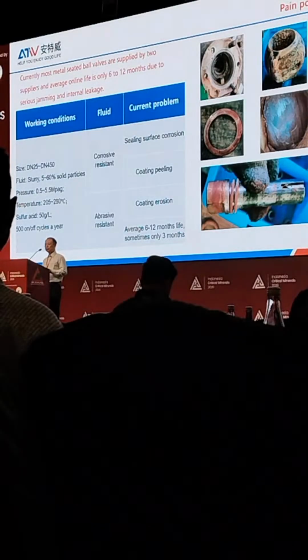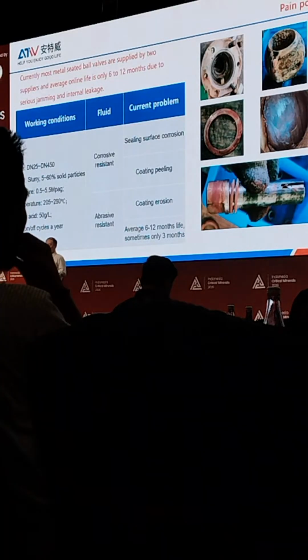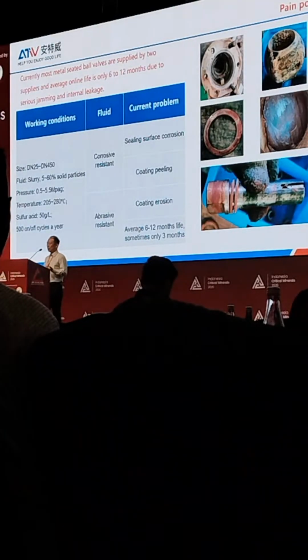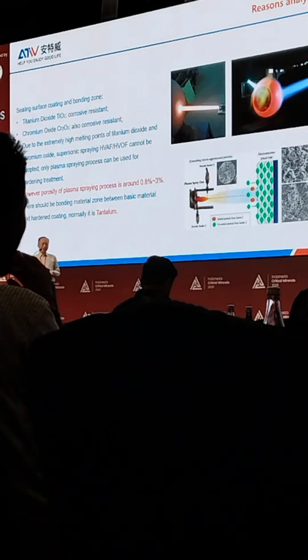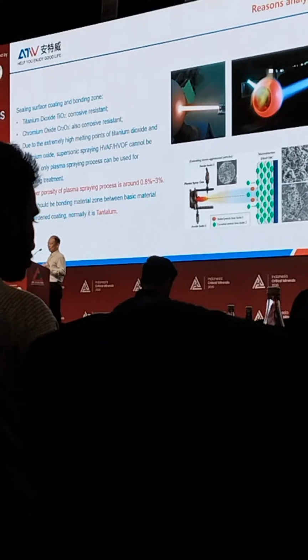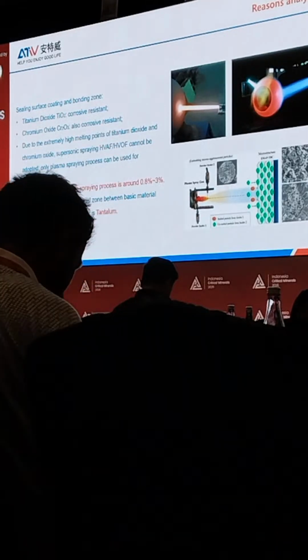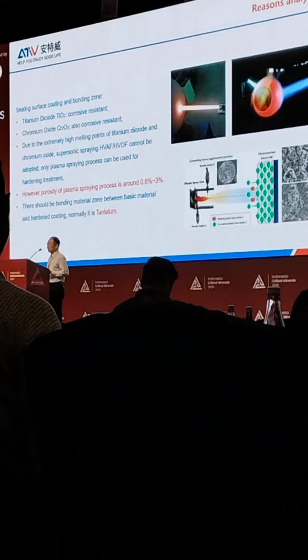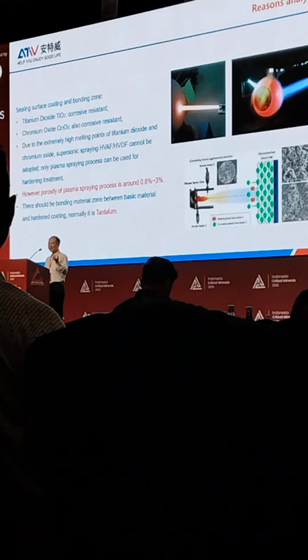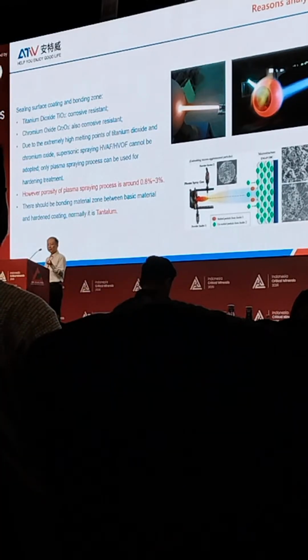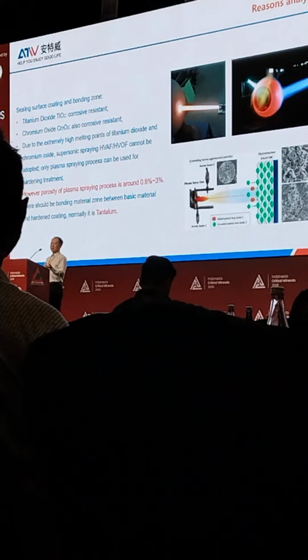And we have many experts to repair these valves. We found the final problems are jamming and internal leakage. We did a lot of research on why it gets internal leakage and jamming, and we found that because the fluid is acid mineral slurry, it must have hard coatings. Normally, for such fluid, the coatings are titanium dioxide or chromium oxide. But both coatings are very hard, and their melting temperature is very high.